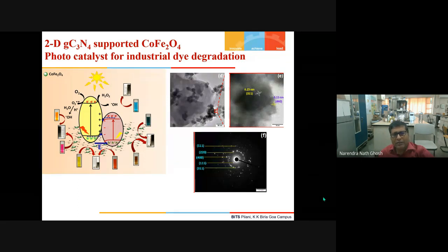So these cobalt ferrite nanoparticles have dual roles. One, they provide catalytically active surface. There are three roles. Second, they act as a spacer to prevent the collapse of the layers of the graphitic carbon nitride. Third, they provide some magnetic character so that you can remove this catalyst after the completion of the reaction easily by magnetic separation process.